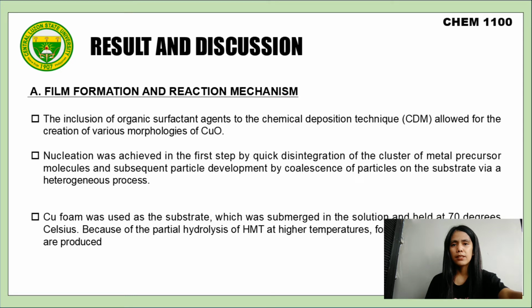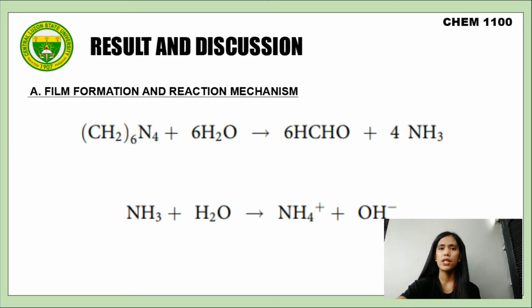Next slide, please. The ammonia produced by the hydrolysis of HMT reacts, and copper oxide precipitates when copper 2+ is combined with it. Further, by generating complex ions, ammonia inhibits precipitation. As the reaction progresses, the concentration of OH- increases, which is usually beneficial to the formation of copper oxide. Cu(NH3)4 2+ releases H2O and NH3 at higher temperature, resulting in the production of copper oxide.